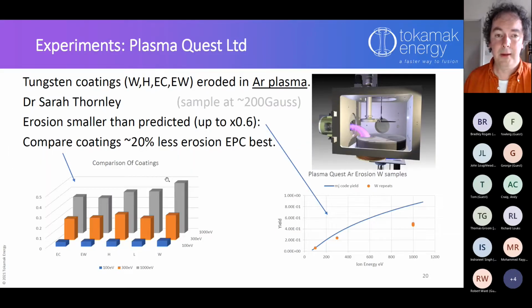So that's quite promising. We did some other work with a company called Plasma Quest, who manufacture plasma sources. This is an argon plasma, so not a helium plasma, but an argon plasma. Argon is much bigger and has the advantage that it erodes the samples quicker, so you're able to do these experiments a lot faster than the other ones. We've got the results down at the bottom here. There's a picture of it up here. So this is the plasma source, and then the samples put down at the bottom here, and the plasma is bent through with an electromagnet to hit the samples.